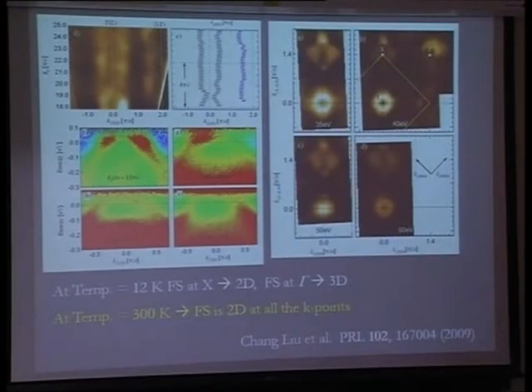So in this paper, what they say has been shown very clearly here: you change the photon energy, and at low temperature, this X point Fermi surface shape looks somewhat similar in all the cases, but at the gamma point, you can see at 35 eV it's quite bright, and at 60 eV it's very different, okay? So you have many Fermi surfaces, like three Fermi surfaces around the gamma point, and all of them are not behaving similarly.